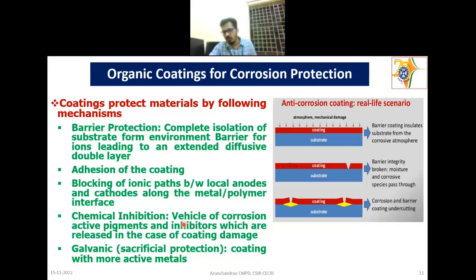Then the adhesion of the coating is another thing. There are two types of adhesion: dry adhesion and wet adhesion. When you apply a coating, we may find that it has good adhesion. But when you keep that coating in an aqueous medium, water or water at 40 degrees Celsius, there is an ASTM test to find out the water resistance and adhesion of the coating. We can find that the coating does not have enough wet adhesion. Then it is blocking the ionic paths between local anodes and cathodes along the metal polymer interface.